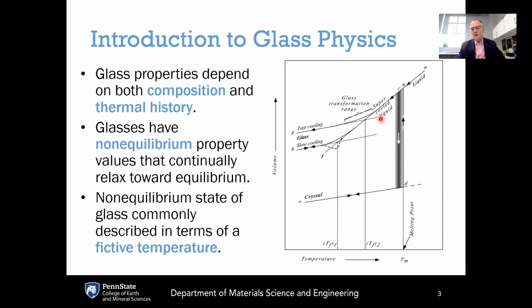From a thermodynamic point of view, this is known as a metastable phase, meaning that if you just leave the supercooled liquid unperturbed, it would be stable on its own. But there is a possibility of lowering the free energy of the system, finding a more stable phase by undergoing a phase transition. So the supercooled liquid, while kind of metastable if it's left unperturbed, can find a more stable equilibrium if it undergoes a phase transition to crystallize.